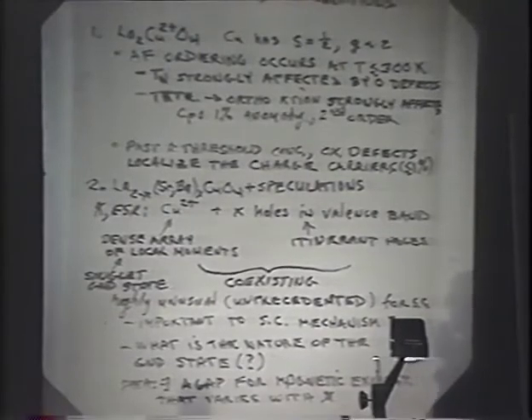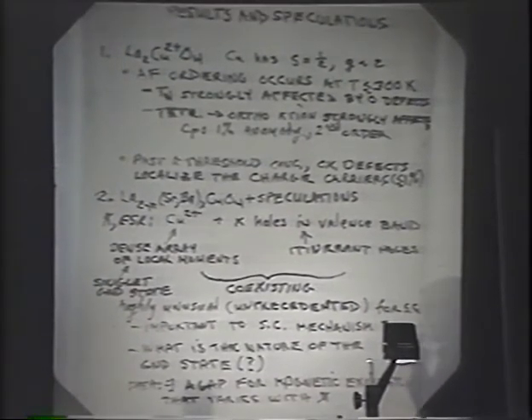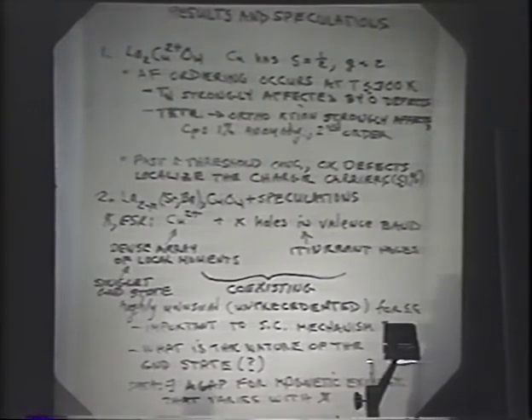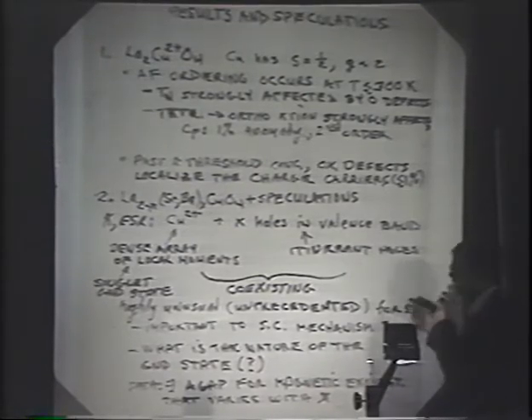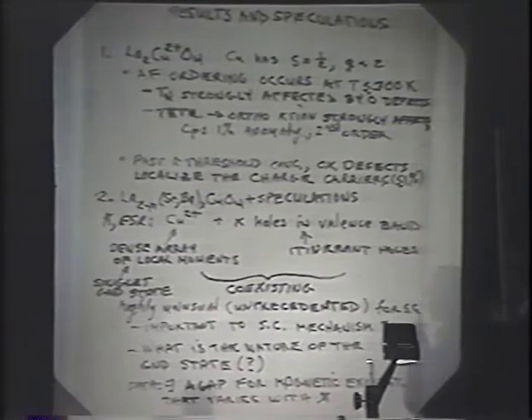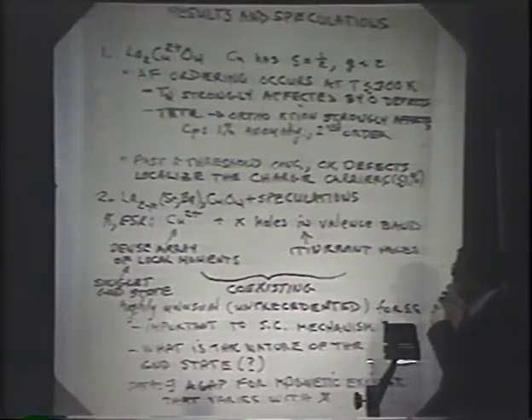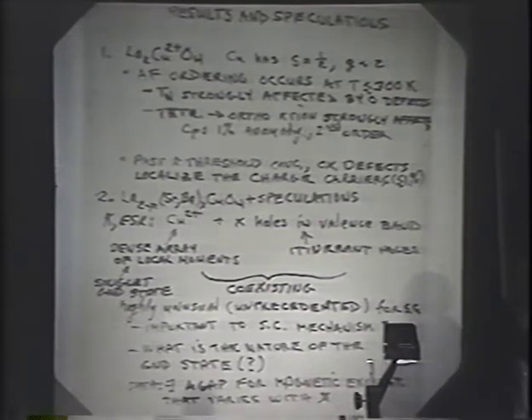To summarize in one minute, it appears that in La2CuO4 the copper is in a spin one-half ground state. Antiferromagnetic order occurs near 300K or below, depending on the stoichiometry. But the one point I'd like to test out on you, experimentalists and theorists alike, is that we would speculate that the strontium and barium doped samples contain a dense array of local moments in coexistence with itinerant holes. This has many ramifications. Thank you.